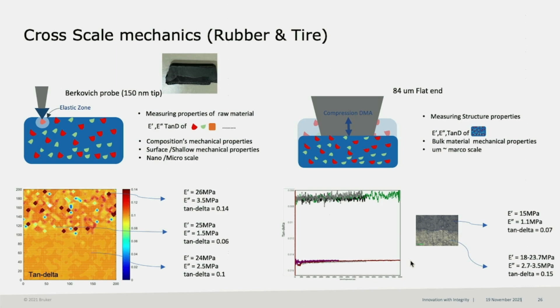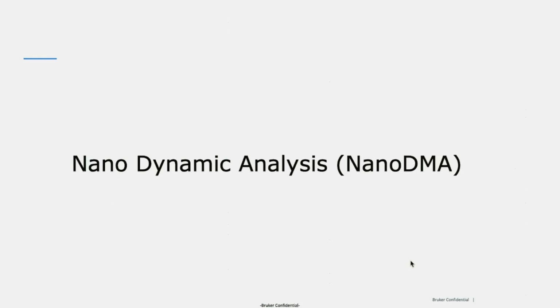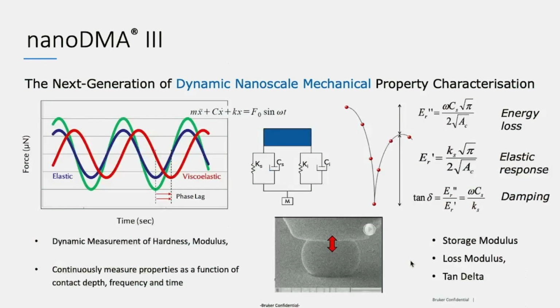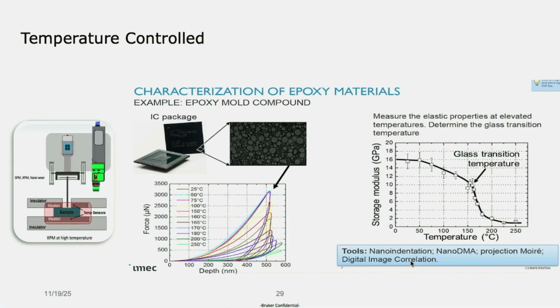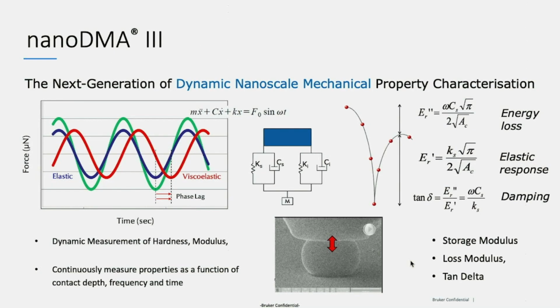So okay, I just gave you two different ideas. One is to use high-speed mapping, and we can stitch a lot of high-speed maps to extend our scale in the XY direction. We also can use a different probe to average our mechanical properties to align with the macro indenter. So we have many different ways to extend our measuring scale, right? This is a very important message I would like to deliver. Nano indenter is not just the nano. We have the nano DMA, right? We can run the DMA and get the E prime, E double prime.